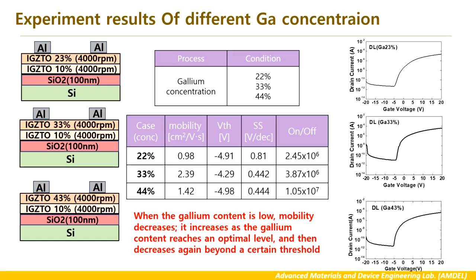We then studied the effects of gallium concentration. When the gallium content was low, mobility decreased. As the gallium concentration increased, the mobility improved and reached an optimal level. However, when the gallium content was too high, the mobility dropped again. This shows the importance of carefully controlling gallium concentration.